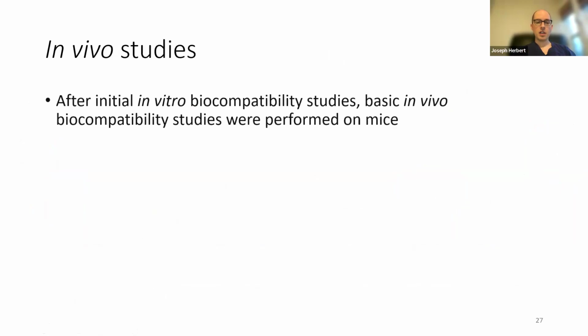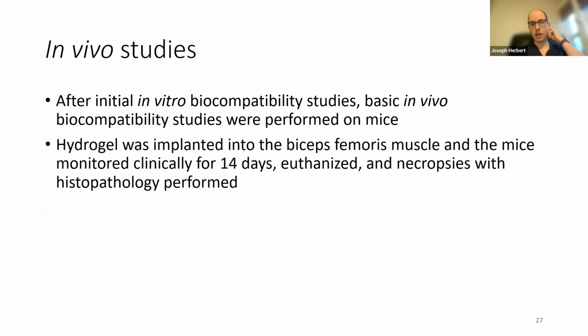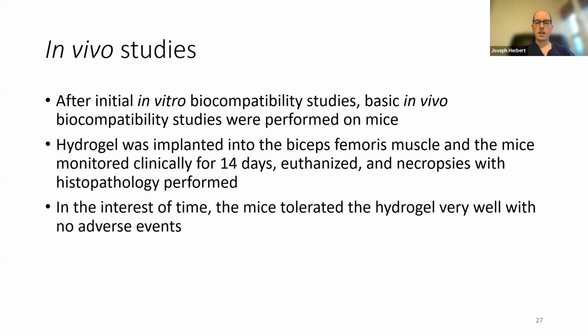So then taking it from cells, we wanted to make sure, of course, that these were biocompatible in a mammalian model. And so we did basic in vivo biocompatibility studies in mice. We implanted this hydrogel into the biceps femoris muscle of a mouse, and they were monitored for 14 days, euthanized, and then necropsies with histopathology were performed. Just in the interest of time, this was very well tolerated. There were no adverse events.